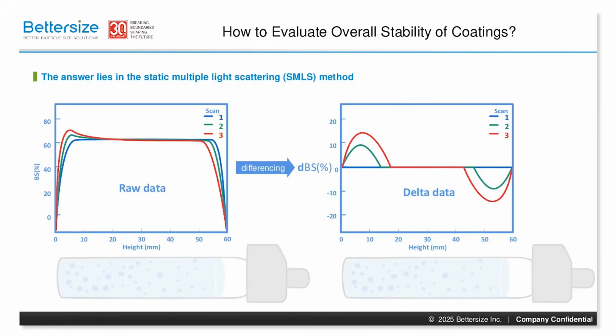The signal collected by the SMLS instrument is recorded into two forms: raw data and delta data. Raw data represents the original unprocessed signal detected by the forward or backward detectors. It's the baseline we use for comparison. The delta data, on the other hand, tells us about change. It's calculated by differencing subsequent scans from a reference scan, which is typically the very first scan. The delta data provides a quantitative method to understand how the sample structure evolves over time.